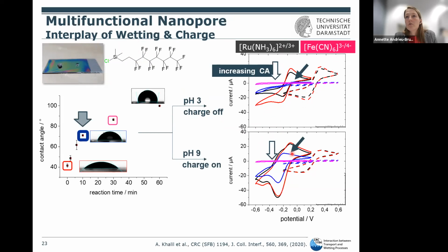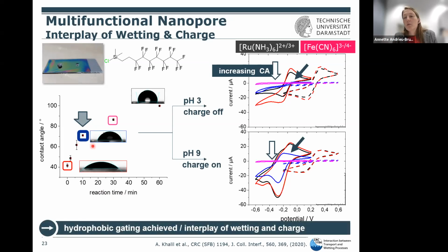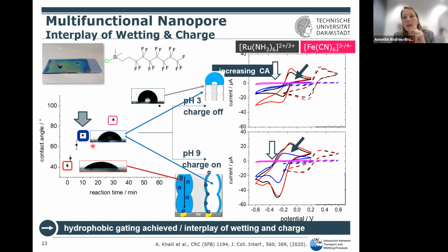The interesting curve here, in our opinion, was the blue one, which at acidic pH shows almost no pore accessibility for the positively charged probe molecule, but at basic pH it does. So there is a kind of switching on, which is wettability related. This is at a contact angle around 70 degrees in our contact angle curve. And the question is how to explain this. I will show you the data, but what we found is that by switching on the silanol groups at the pore wall, you probably get a condensed layer of water through which the transport occurs. An indication for this is also the shape of the CVs that you see. Below this contact angle, you have water-filled pores, and above this contact angle, you have water exclusion even at basic pH.